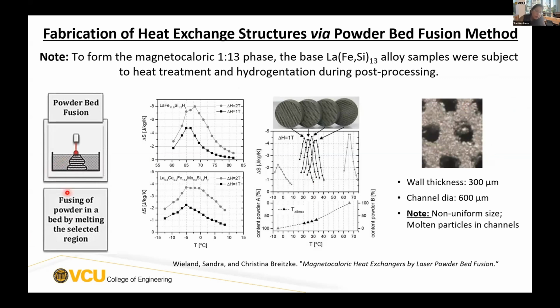Powder bed fusion is a technique where there's a bed of powder, and you fuse it by melting a selected region with the help of a laser. In this study, a base alloy of lanthanum iron silicides was used, and once the net shape channels were printed, they were subjected to heat treatment and hydrogenation using post-processing.